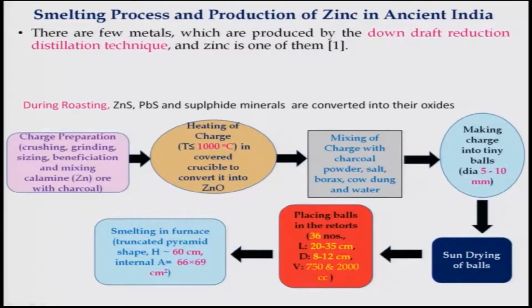of course wood charcoal, and then salt and borax, and then you use cow dung and water so that it binds properly. Then you make pellets, ball size around 5 to 10 mm, and these pellets are sun dried. These pellets are put into retorts of length around 20 to 35 centimeters and diameter 8 to 12 centimeters. Of course, two volumes were used in ancient times, one is 750 cc, and the other was a little larger, more than double, that is 2000 cc.